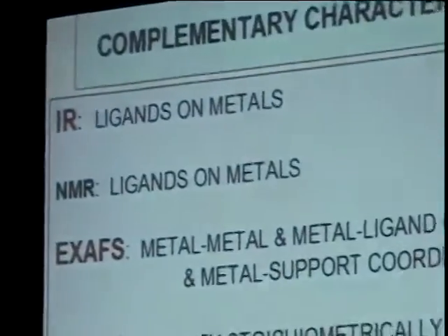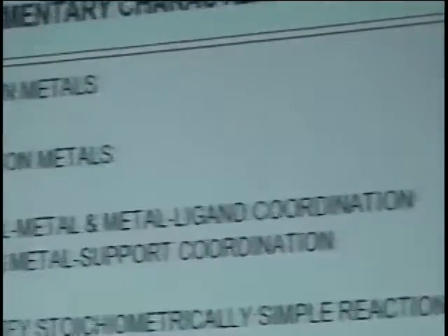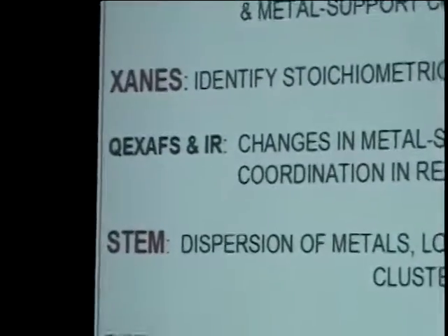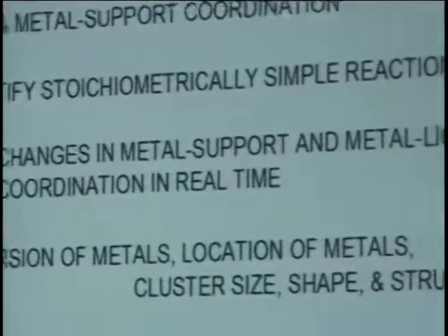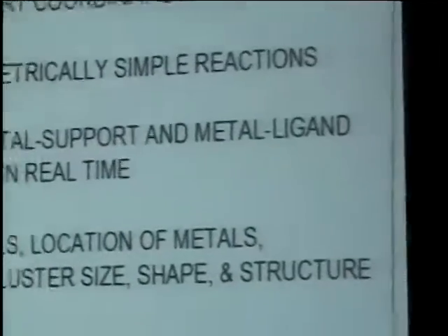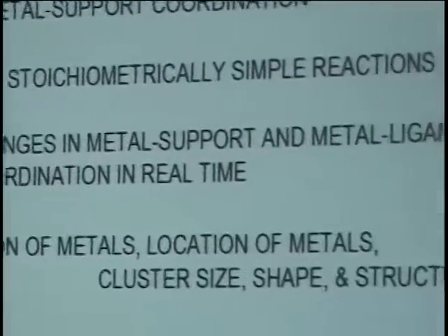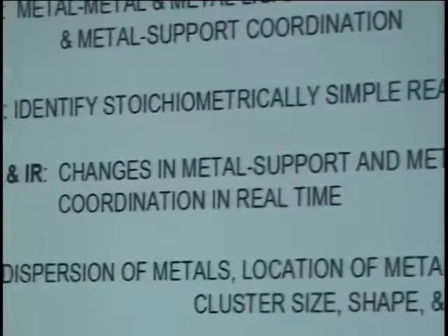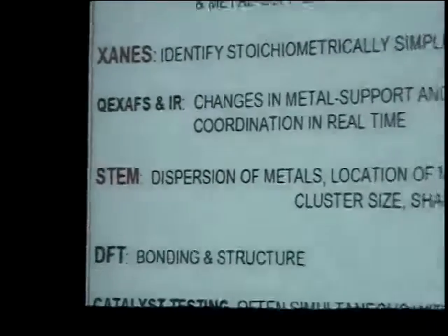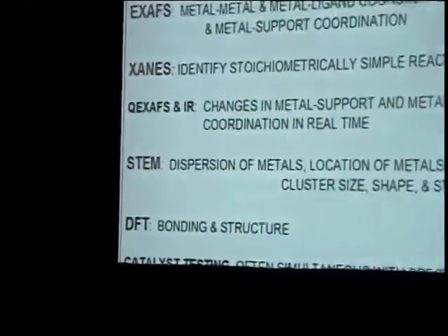The carbonyls give a lot of information in the infrared spectrum. XAFS is crucial for all of this to get structural information that complements the microscopy, or probably I should say vice versa. And XANES, it turns out, we're learning is especially important to track conversions of one species to another.